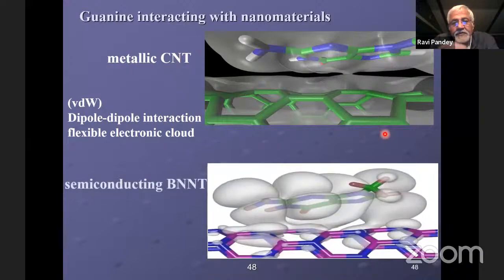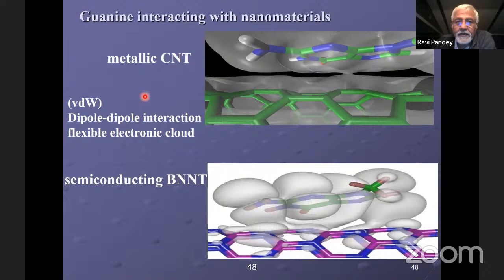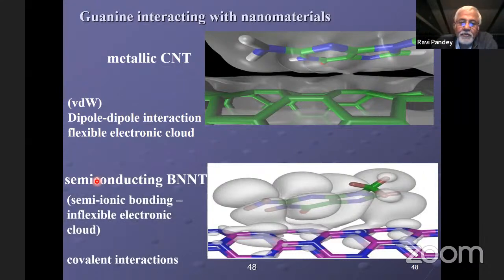And what we came out with, again in terms of fundamental understanding, is that if you look at the metallic CNT, the interaction between the carbon nanotube and DNA is going to be a dipole-dipole-like interaction because of the flexibility of the electronic cloud coming from the nanotube and DNA molecules. And what we call a VDW, a van der Waals type, is very weak. As you switch to boron nitride nanotube, which is semiconducting, and as a previous speaker also talked about, the boron-nitrogen bond is going to be semi-ionic compared to the carbon-carbon bond. So you expect the bonding to be different.